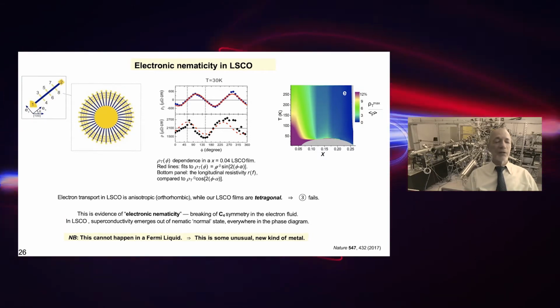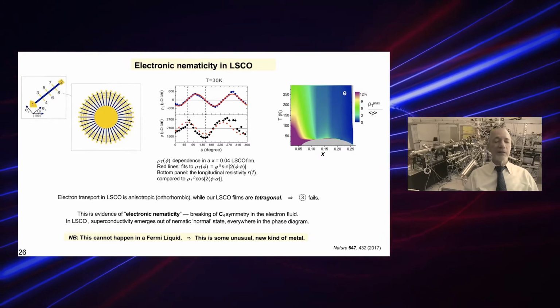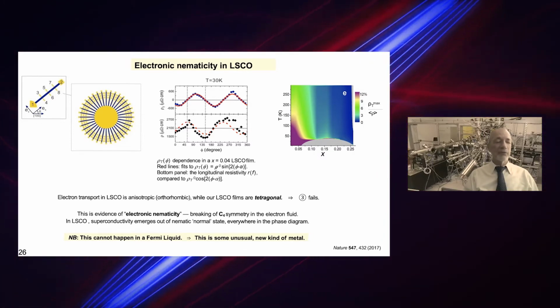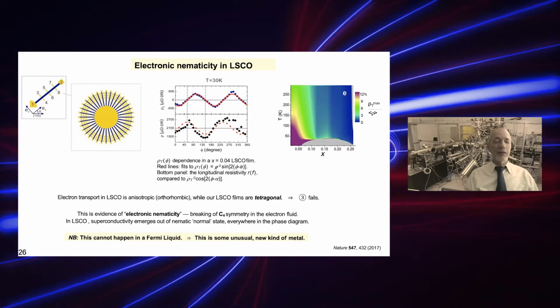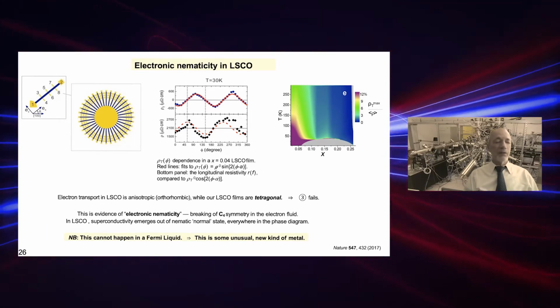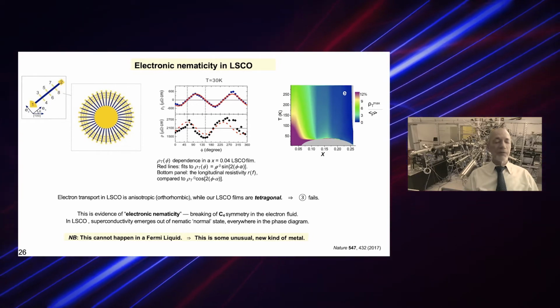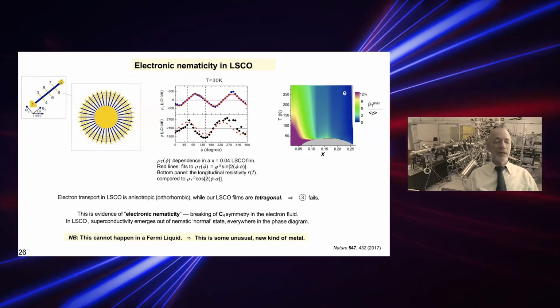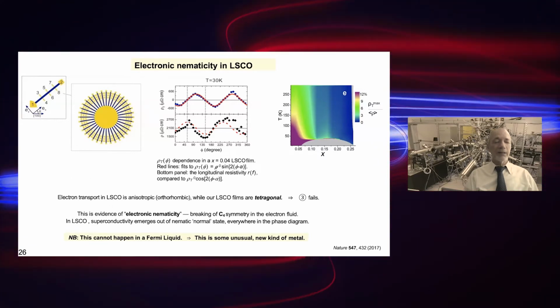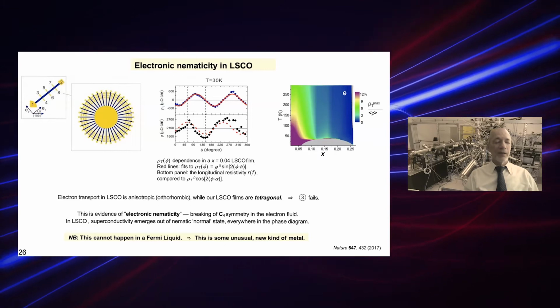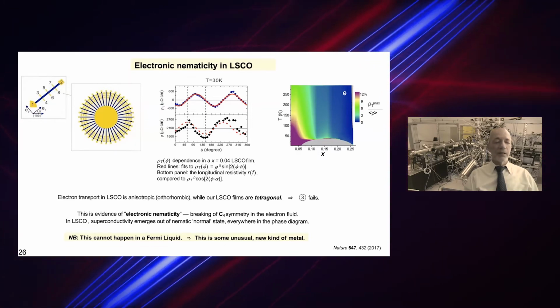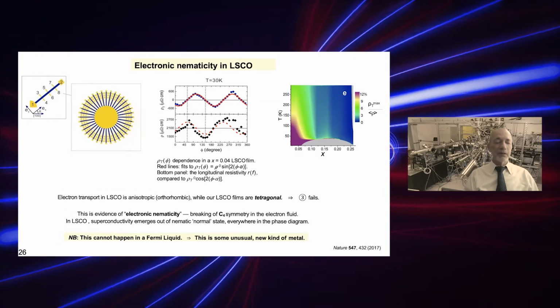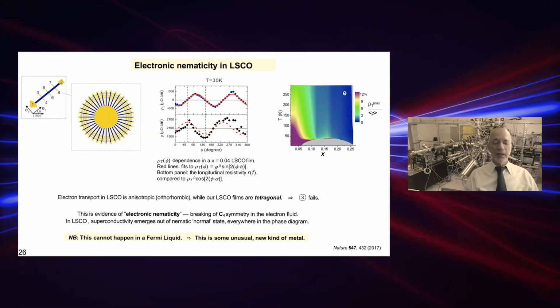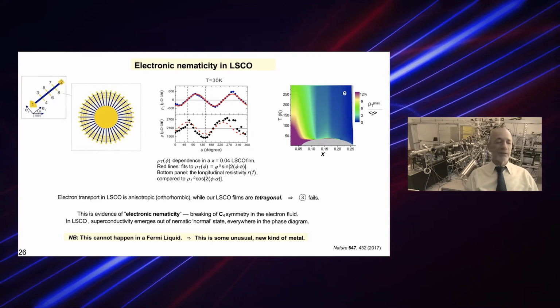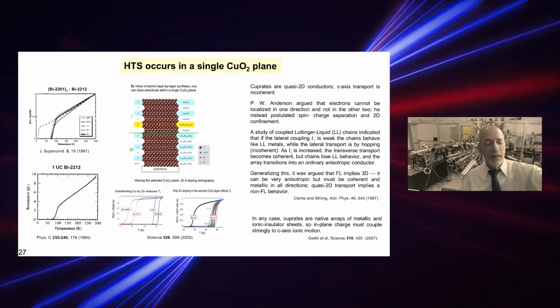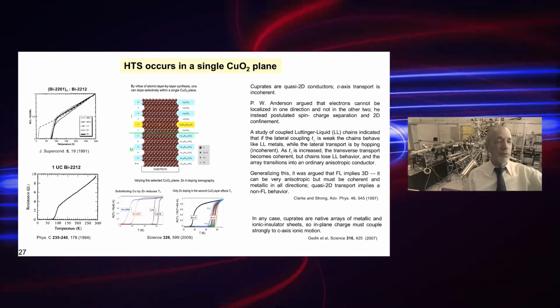Moreover, the orientation of the easy direction of high conductivity is not aligned with the crystal axis. It varies with doping, and it even rotates with temperature. This all shows that this anisotropy is essentially just in the electronic liquid. It's uncoupled from the lattice. And in modern parlance, this is called electronic nematicity. Of course, this could not happen in a gas or in a Fermi liquid, which is a kind of gas of charged quasi-particles.